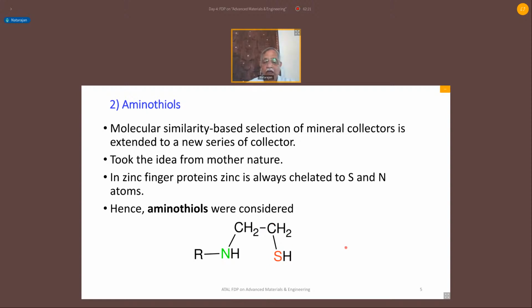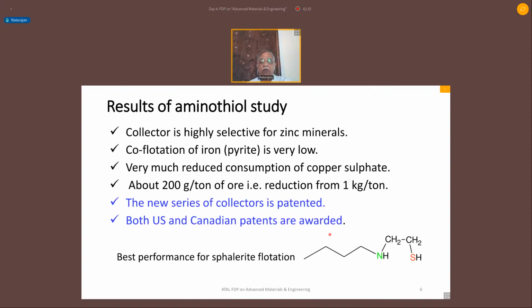So we created a database of about 200 compounds, did a similarity clustering, selected these compounds and tested them, and we found that the aminothiol collectors that we synthesized are very effective, and very selective for zinc mineral. They floated pyrite, but only a very, very small percentage. That means the pyrite contamination is less than what is being achieved even in present mill operations.